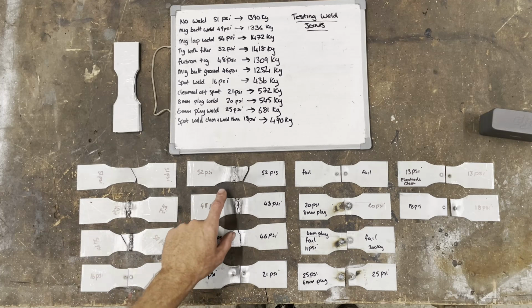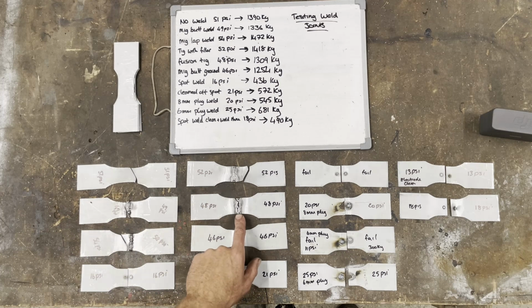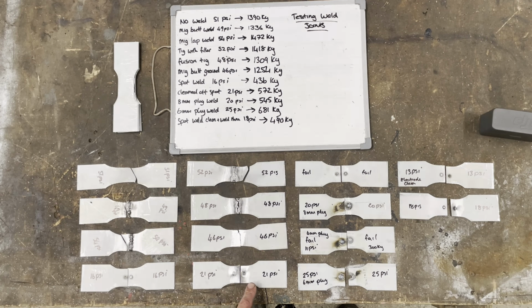If we look at the TIG, the fusion TIG, I expected to be a bit weaker than that, so it was surprising how strong that was. I was glad to see that the MIG weld ground down had very little difference in strength, so pleased with that. The spot welding I was disappointed with. I thought that would be stronger than it was. I expected to see a hole and a slug. I didn't see that, and I can't get that to happen pulling it apart in a tensile strength test.